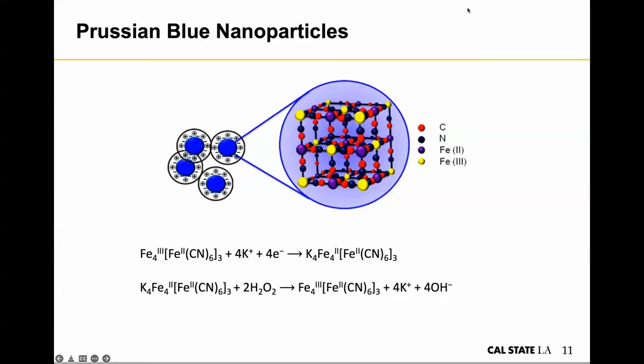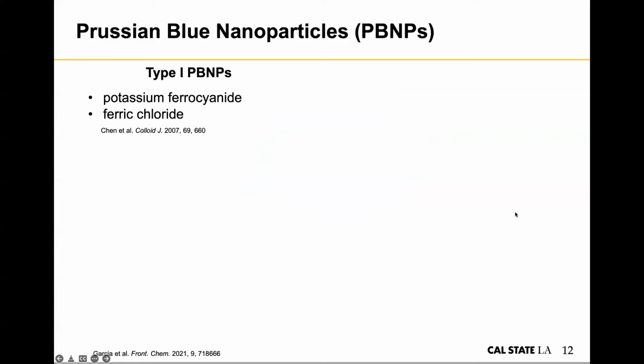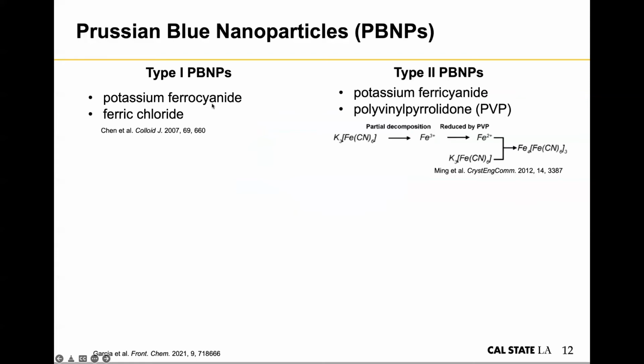The first part we tried to do is survey the literature and look for different methods of synthesizing Prussian blue nanoparticles, because according to the literature, you can use different methods to control the geometry of the nanoparticles that are synthesized. In this case, we used 2 different methods. One is simply combining iron 3 salt with iron 2 salt, so it's a direct synthesis. The other one utilized PVP as a controlling agent, so it's a slower process.